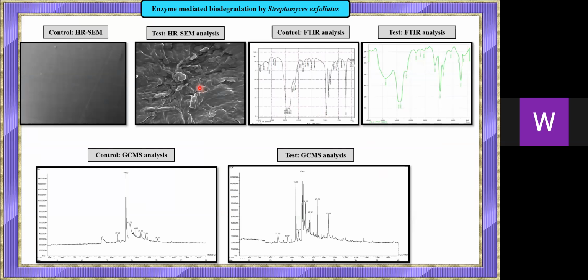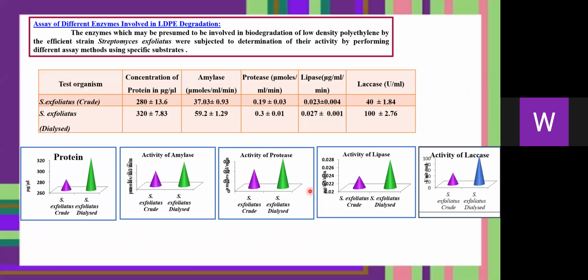This slide shows the images for SEM, FTIR and GCMS compared with control. So varied surface changes are seen in the SEM analysis and also in FTIR and GCMS analysis, showing that the enzyme attack has influenced the degradation of LDPE. Assay of different enzymes involved in LDPE degradation. The enzymes which are presumed to be involved in biodegradation by efficient strains were subjected to determination. It was found that compared to crude extract, the dialyzed sample of Streptomyces exfoliatus showed a great increase in the protein concentration, amylase production, protease production, lipase production, and laccase production.